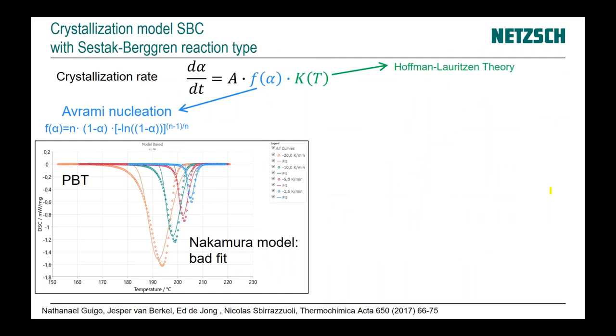Another model which could be used for cases where Nakamura doesn't work — here we have PBT for cooling and use Nakamura — it has very good fit during the cooling for high temperature at the beginning of crystallization, but the Nakamura model works not as well at lower temperatures toward the end of crystallization. We can apply a model published by Nicolas Sbirrazzuoli where instead of Avrami, Sestak-Berggren crystallization was used with Hoffman-Lauritzen.